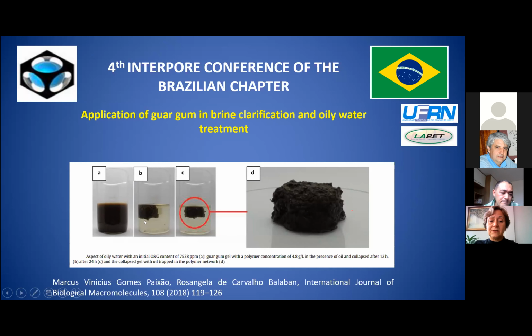In the first minutes occurred the gelation of guar gum, and along the time, these gels collapsed, trapping the oil. So you had the clarification, the salinity was maintained, but without particles in suspension. And the oil was concentrated inside the hydrogel, guar gum hydrogel.